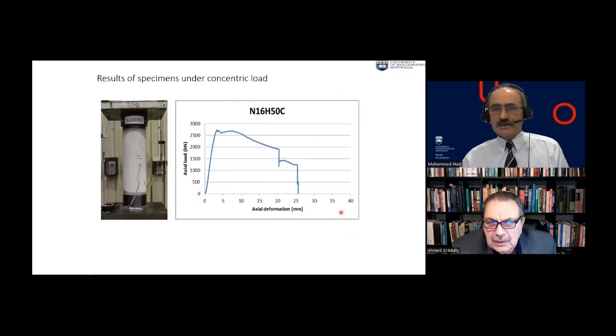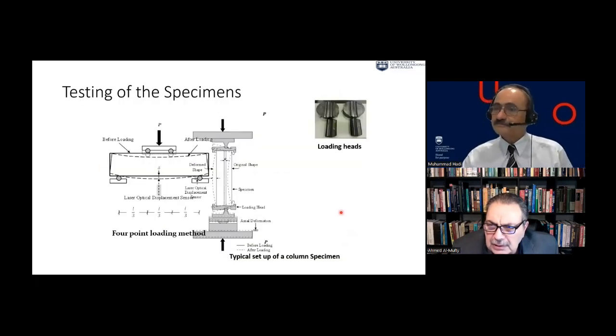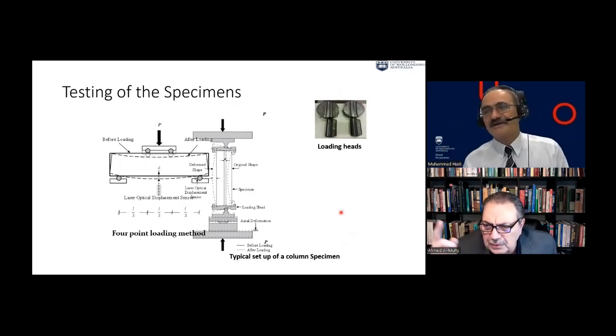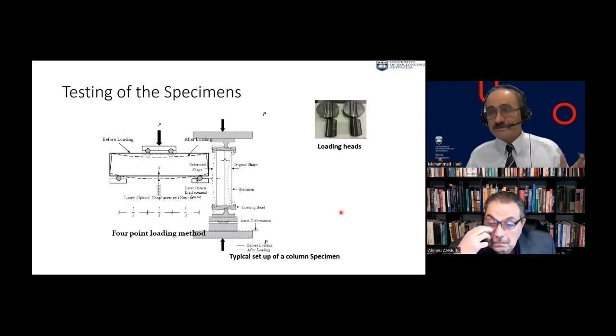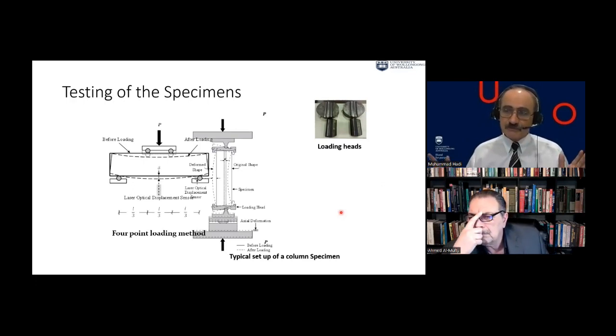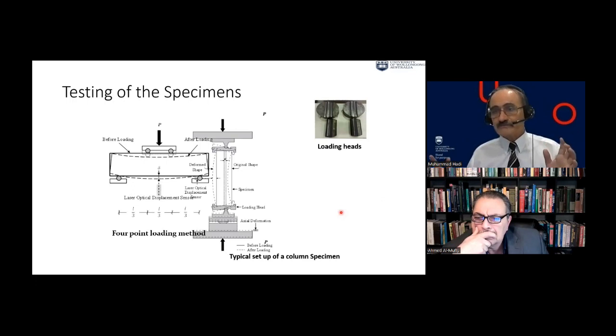So we tested those. And what day do you test after the casting? 28. And did you do crushing tests on the concrete at days, for example, 7, 14, 28, 56? Okay, so what we do in general is 7 and 28. We don't do 14, we just do 7 and 28. Because there are 20 specimens, there's no way we can test them in one day. We test a maximum of 2 to 3 per day. So what we do, we test in compression 3 cylinders the first day of testing, and then another 3 at the last day of testing.